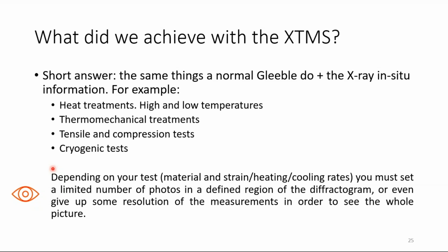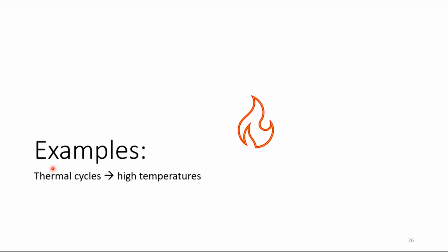It depends a lot on the state of your material. If you have a deformed material, it's going to have poor quality diffractograms. But if you have a very crystalline material, it's easier to get high quality diffractograms. So you are going to test and spend some time. Probably you need to test before, get some information about the dilatation of your material, how the volume transformation is, and then you can move forward to use the X-ray facility. Okay, I'm going to show you some examples of thermal cycles, tensile and cryogenic tests right now.